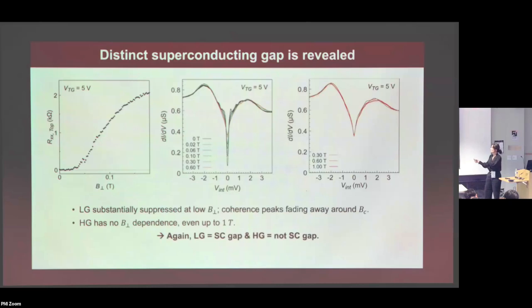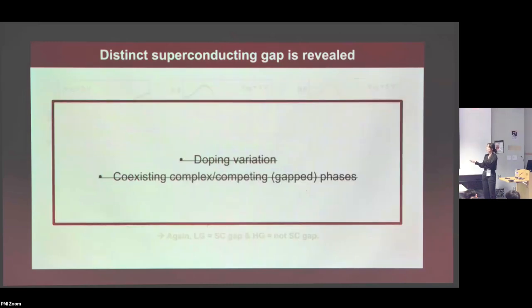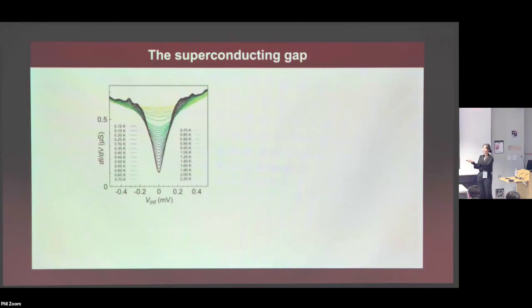So from this, it's sort of, again, evident that the low energy gap is the superconducting gap, and this other thing is something else, whatever that is. So now, at least we sort of got rid of this mystery. Is there coexisting stuff? There seems to be coexisting stuff.